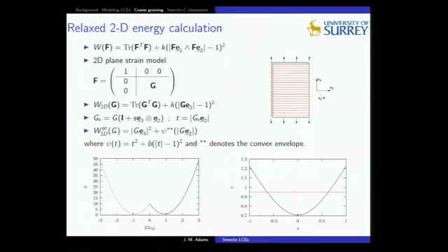What that does is flatten out this bit of the energy because you can always sit in this minimum with the right amount of shear as you deform the sample and change this GE2 down here. So that's where you get your convex energy back from and iron out this fold that I showed you in the energy earlier.